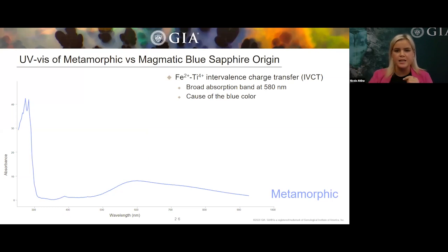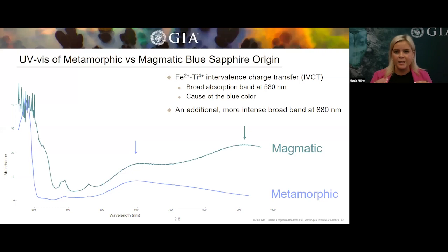And so you can see that it has this broad absorption band at 580. And this is an intervalence charge transfer of an iron 2+ and titanium 4+. So this band right here at 580 is what's causing that blue color in our stone. And so when I overlay it with a magmatic, the magmatic does have that 580, but it also just has this additional more intense broad band at 880.